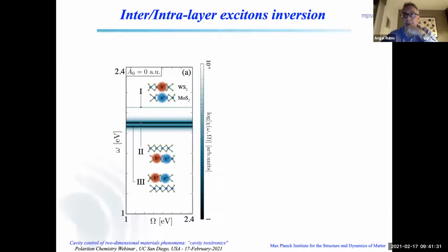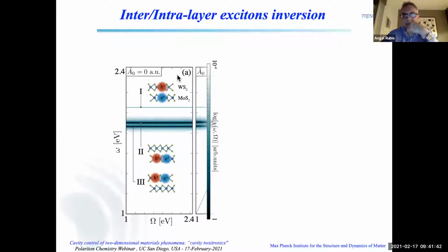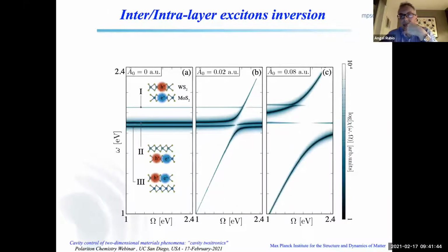The question is, what are the implications of this in a real material? Let's take, in this case, tungsten and molybdenum disulfide, and you have the intralayer exciton and the interlayer exciton. The order of energies in reality in the experiments is this one: you have the intra below and the inter above in energy. Then the question is, what can we do when we put these materials in the cavity? And I do exactly the same thing I showed you before. I put it for a weak coupling and a strong coupling regime.